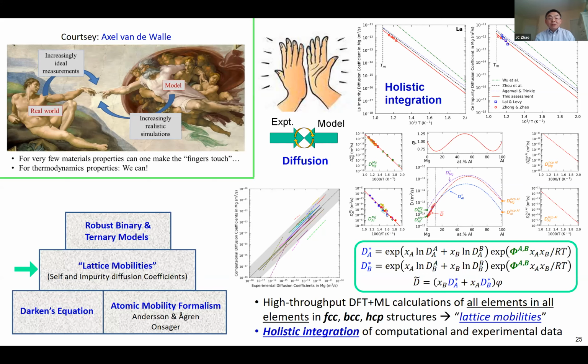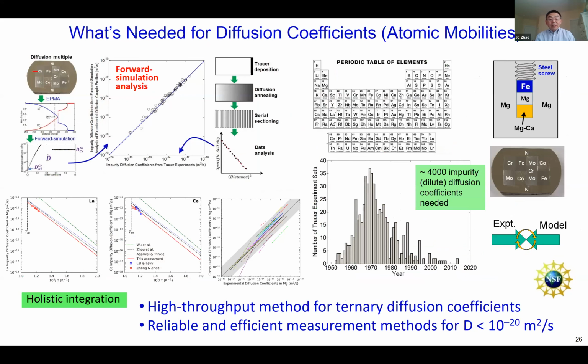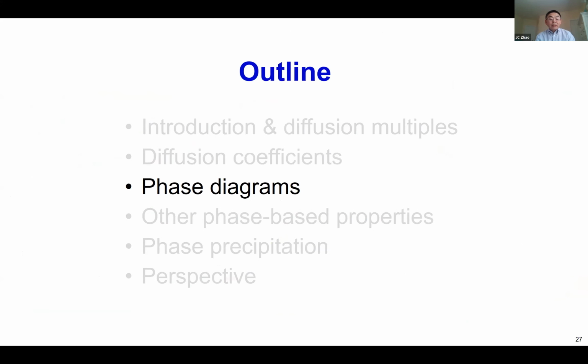So as I mentioned, I'm going to focus on diffusion. On the experimental side, the methodologies we developed are very effective, but we still need to develop a methodology to more efficiently measure ternary diffusion coefficients. I have an NSF program right now to do that. We also need to develop a methodology to use the long tracer method to measure diffusion coefficients down to very low values. Right now, there's not a good method to do that.